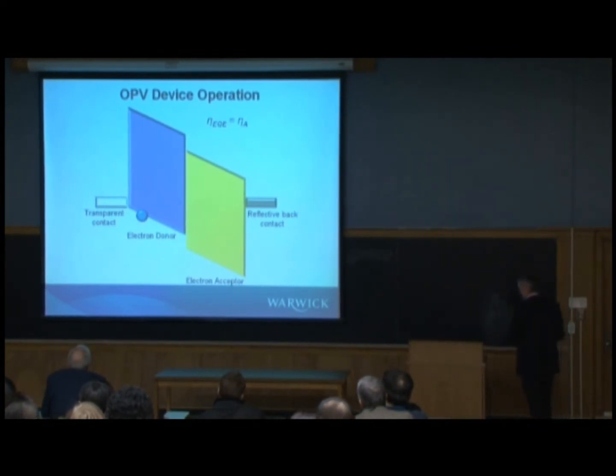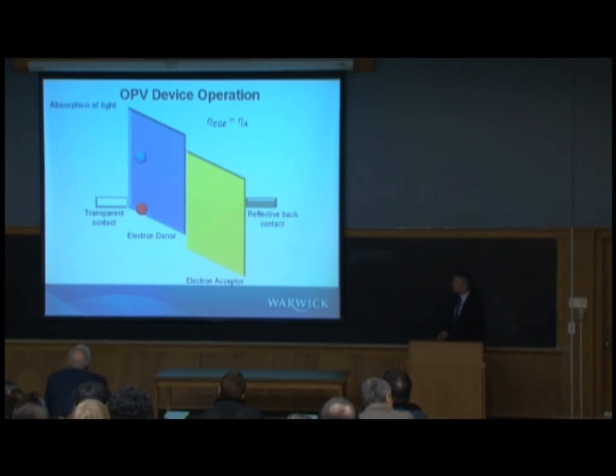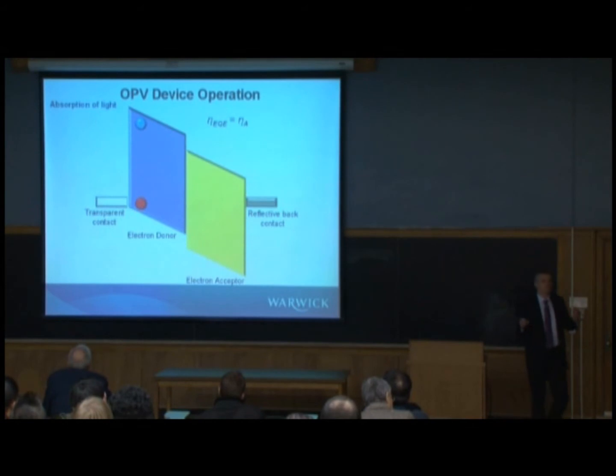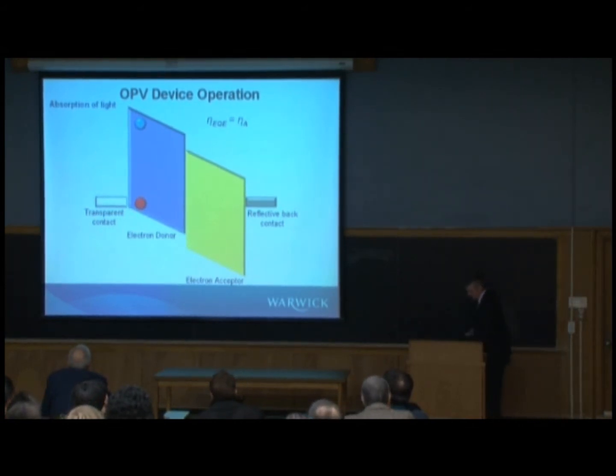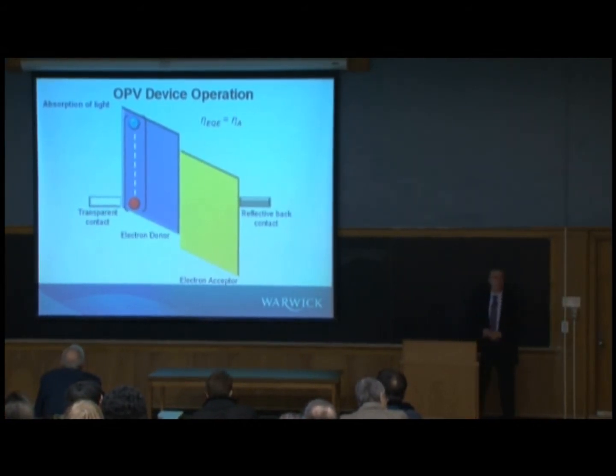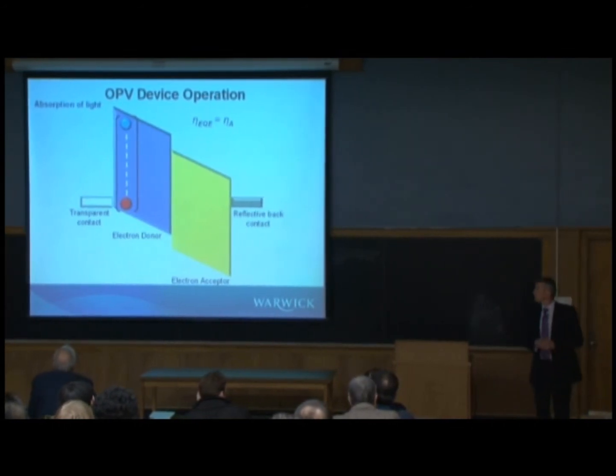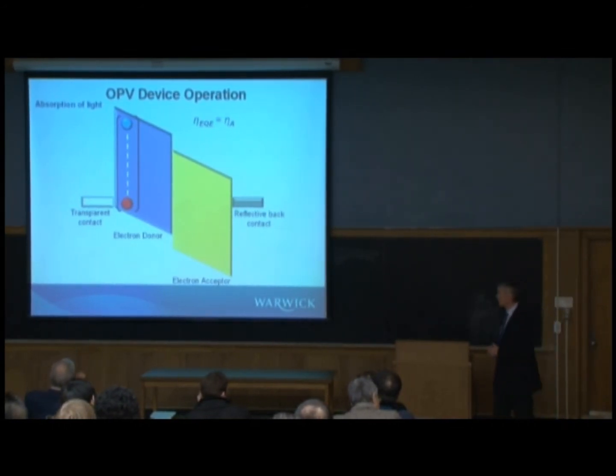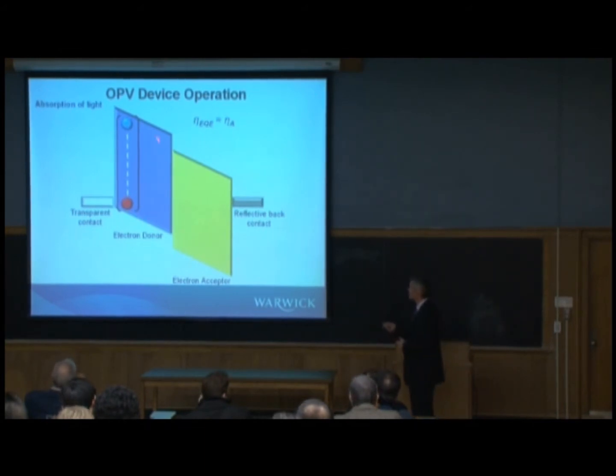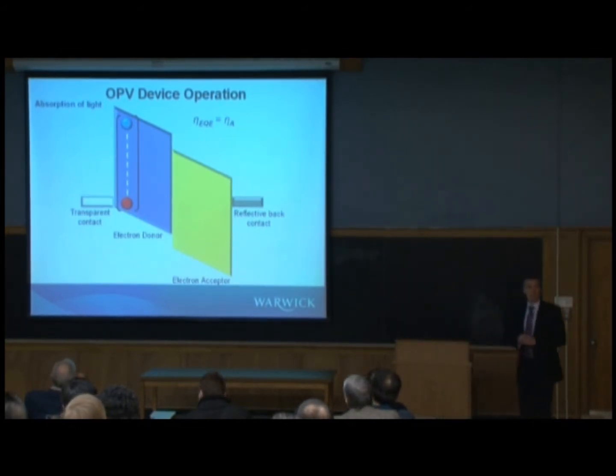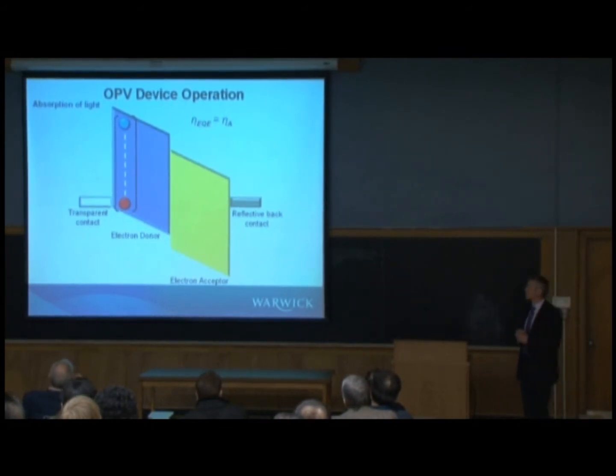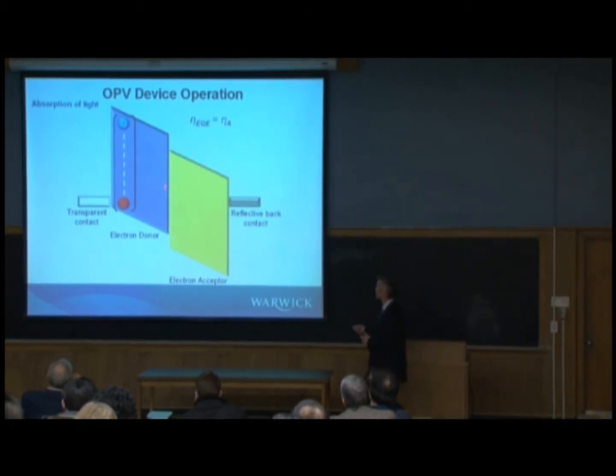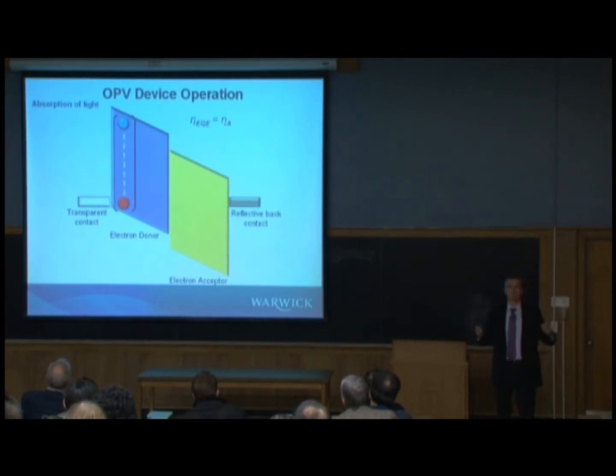So in the basic device, you have sunlight. In the donor, in this case, it could be in the acceptor, we generate our excited state, our exciton, our electron-hole pair, which is highly localized, remember from the previous slide. So the first step is the generation of the exciton, strongly bound. Now, in order to extract charges, that exciton has got to get to an interface. There's got to be a driving force to dissociate the exciton and separate that electron and that hole so we have the free charges to generate our current.